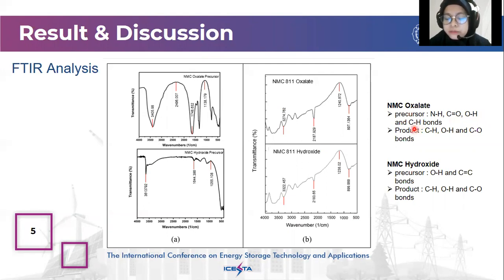And after calcination, the NMC oxalate product presents carbon bond to hydrogen, oxygen bond to hydrogen, and carbon bond to oxygen. For NMC hydroxide, the precursor indicates oxygen bond to hydrogen and carbon bond to carbon, and the product after the calcination of NMC hydroxide presents carbon bond to hydrogen, oxygen bond to hydrogen, and carbon bond to oxygen. It can be seen that the two products have the same constituent groups: carbon bond to hydrogen, oxygen bond to hydrogen, and carbon bond to oxygen group.